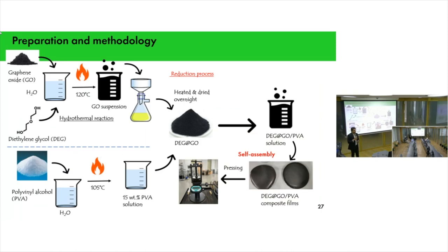For the preparation and methodology, graphene oxide was reduced by the hydrothermal reaction method, and by this method it induced self-assembly. After the self-assembly, the composite system was pressed for 10 minutes at a high force to remove the bubbles and the defects from the system.